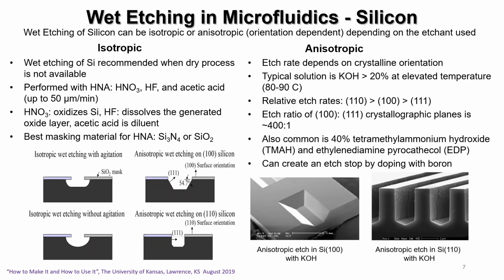Again, silicon is nice because you can make a masking layer by using silicon dioxide. And the etch rate of all of these chemicals into silicon is fairly well described. And if you look at here, you're using nitric acid, oxidizing agent, hydrofluoric acid, it's dissolving the silicon, and acetic acid is just a diluent here. So you mix these chemicals up, and when you have this masking layer here and this silicon that's exposed, you're going to get, is this isotropic or anisotropic? It's undercutting, it's isotropic. So nitric acid, hydrofluoric acid, acetic acid mixed up with silicon with some masking layer is going to give you isotropic etching.